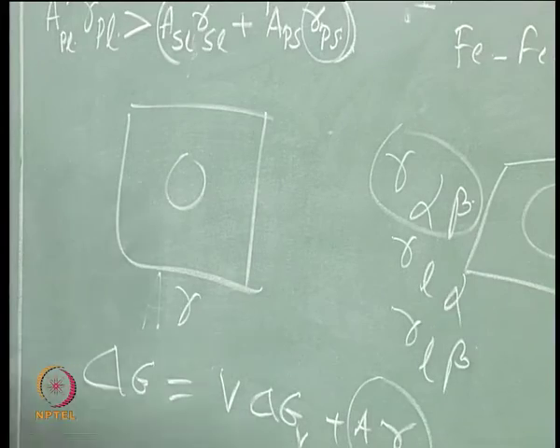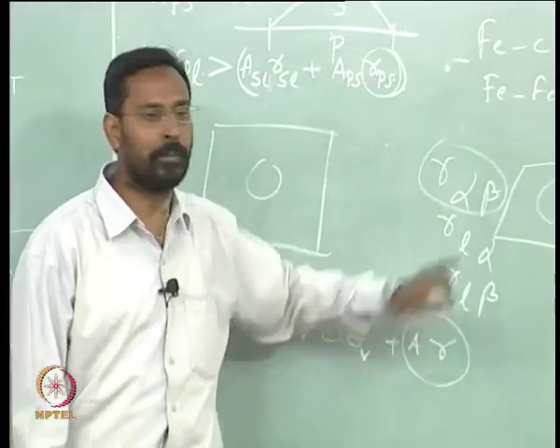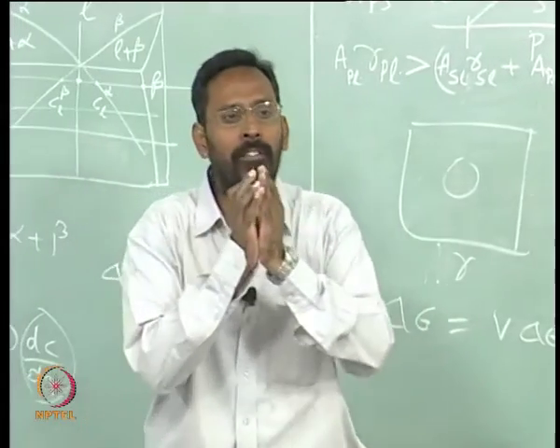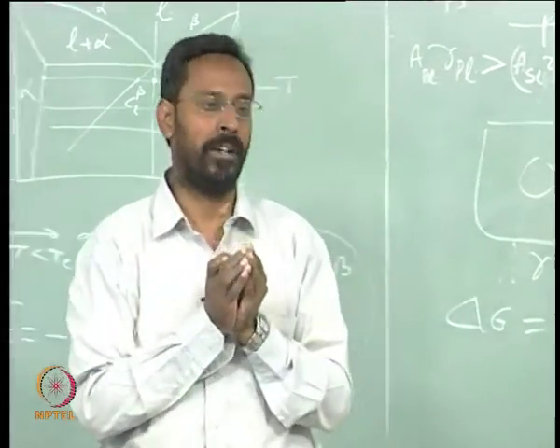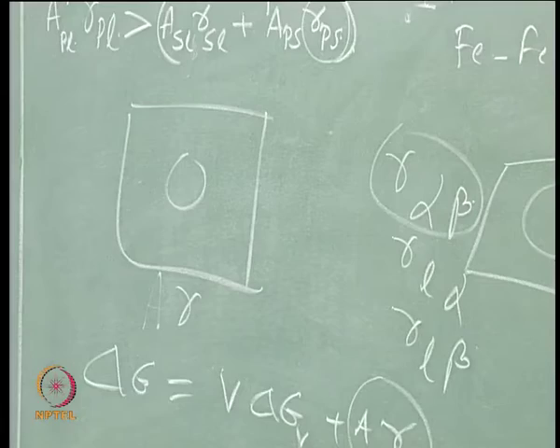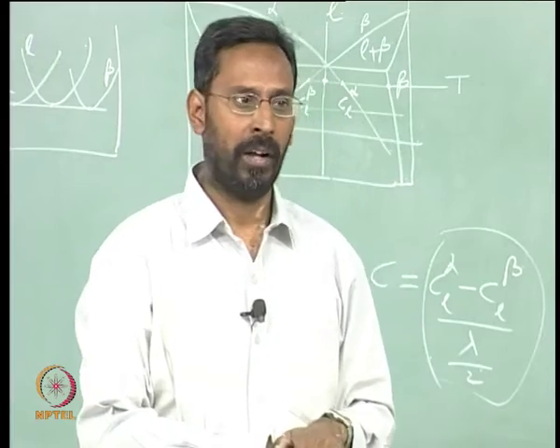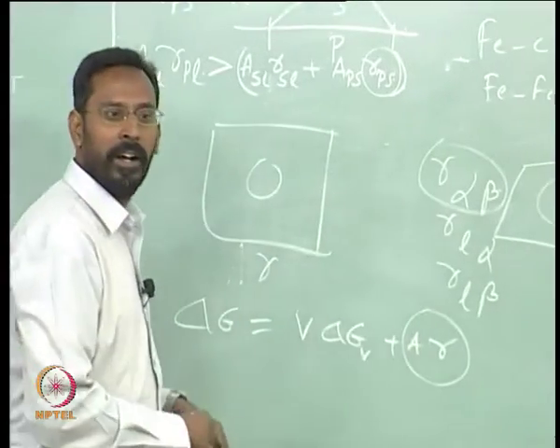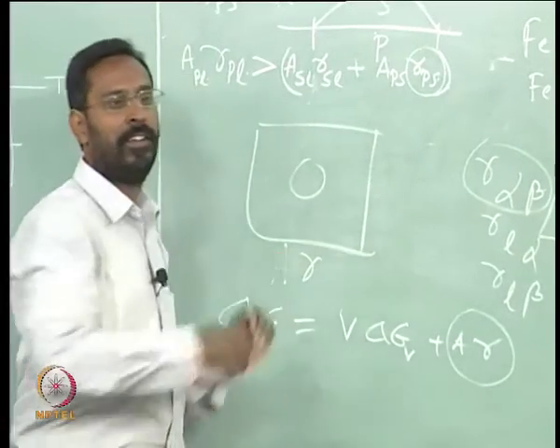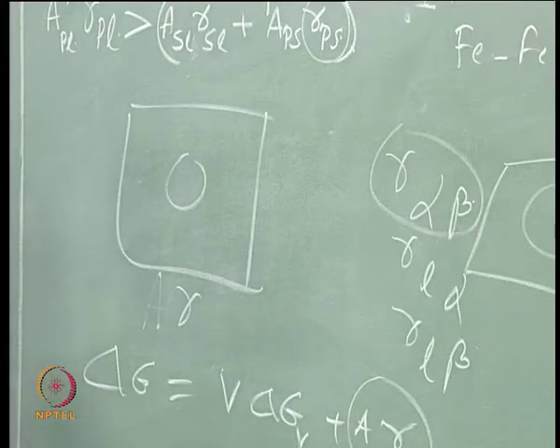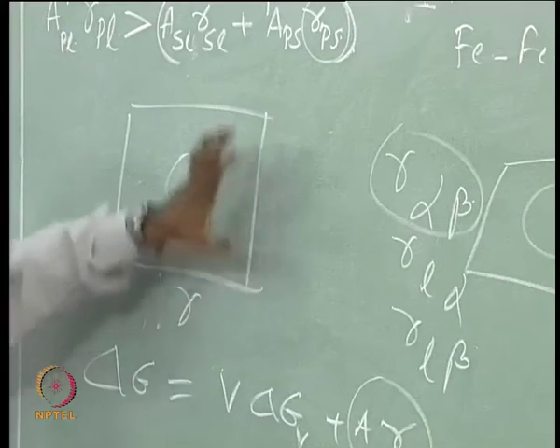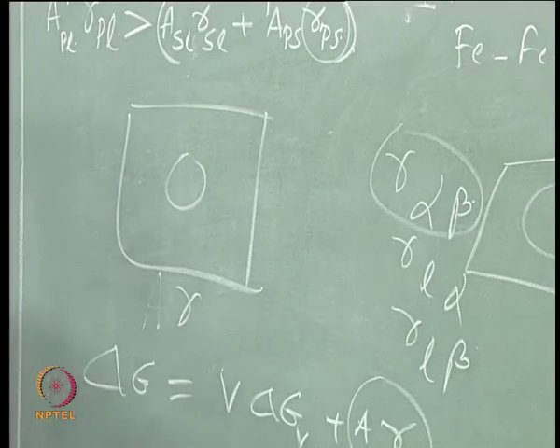The moment liquid-alpha interfacial energy is smaller, alpha and beta will never nucleate together as a couple. You will see alpha nucleating first, and then the remaining liquid slowly converts to beta, so you end up with a beta matrix and alpha particles.